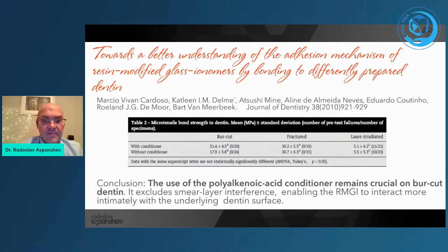If we are using, for example, burs or excavators, or the tooth is fractured, then there is not much of a difference whether we use conditioner or not. Same if the tooth is treated with laser. But as this study from the university in Leuven, done with a couple of my friends, shows, especially when the burr cuts dentin, it is crucial to use polyalkenoic acid conditioner to remove the smear layer and to allow the glass ionomer to react intimately with the dentinal surface.